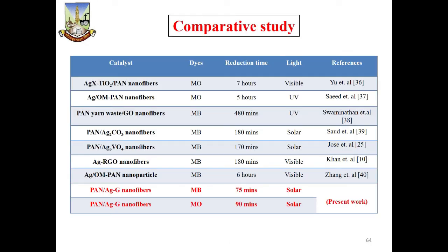This is the comparative study. We have compared with previous studies. PAN AGG nanofiber degrades methylene blue at 75 minutes under solar light, and PAN AGG nanofiber degrades methyl orange at 90 minutes under solar light. In previous studies, they have taken much more time: 7 hours, 5 hours, 480 minutes, 180 minutes, 170 minutes, 180 minutes, 6 hours. Much more time is required in the presence of other nanoparticles and nanofibers, but this material is found to be very effective.